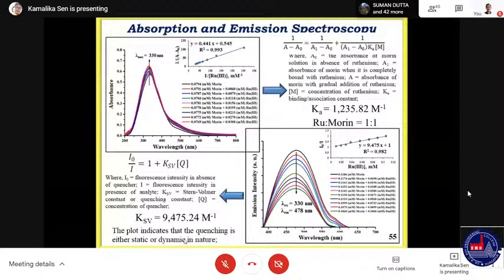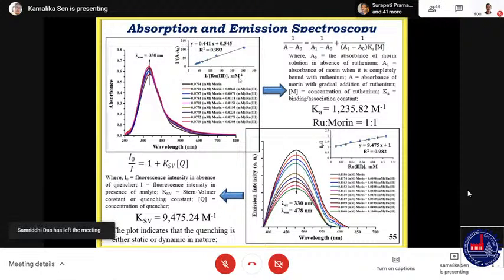This is the absorption and emission spectroscopy. We can see it is a little clumsy. This is the absorption spectrum. We can see at 330 nanometer, Morin shows an absorption peak, which increases with addition of ruthenium-3. And if we try to plot the Benesi-Hildebrand plot, we can find the association constant between Morin and ruthenium. That means there is a sort of complexation occurring between ruthenium and Morin.